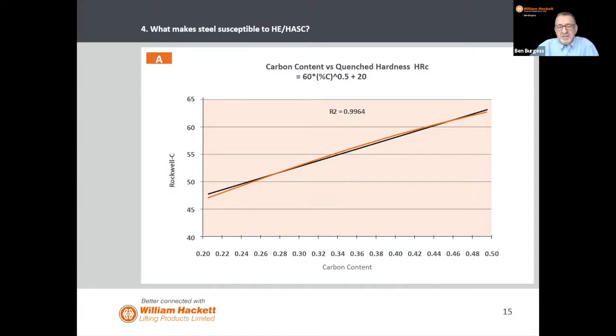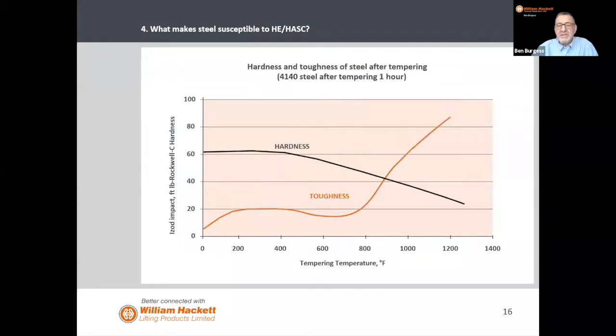The other subject we touched on there was heat treatment, and with Francois and Professor Rolf Mustard, they are absolute experts in this. So for a given grade of steel, if you temper it at 200 degrees for a very low period of time, you end up with a steel that is extremely hard and in effect would give you a good working load limit. However, its toughness is not very good. If there's a snatch on the load, corrosion, it's not great.